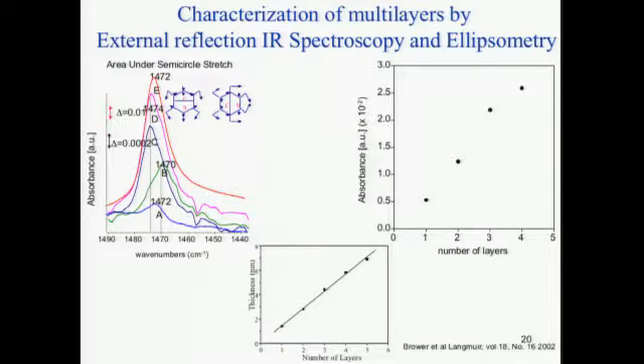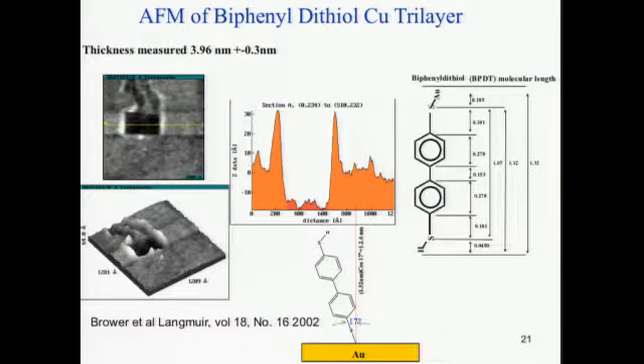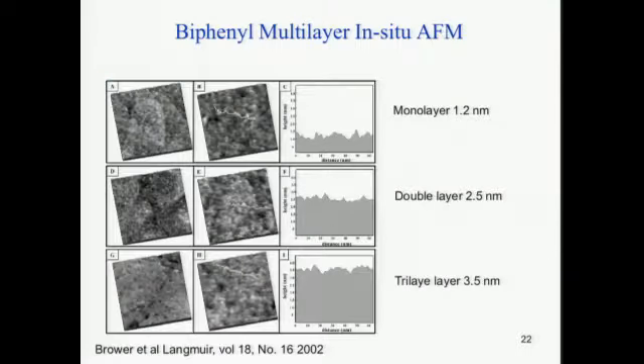And also, if you look at the relationship between the number of layers and the absorbance, we can see that it's a linear relationship. And also, the thickness is a linear relationship. The thickness corresponds to the number of layers based upon the size of the molecule that I described to you earlier. And furthermore, using the nanografting or nanoshaving technique, the thickness measured by AFM is about 4 nanometers, where one molecule is about 1.32 nanometers in size. So taking these things into account, we're pretty confident that we're making a multi-layer system.